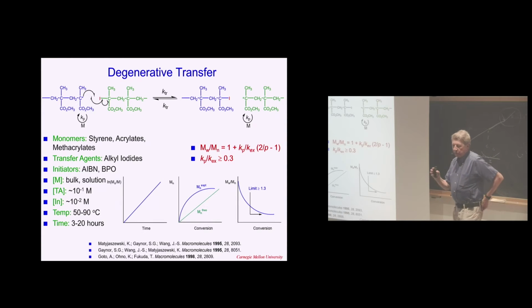So I will give you some examples of these reactions. One of the probably simplest is really with alkyl iodides. It is not a very good system, but it's somehow working. And you could see here what happens. You take alkyl iodide, which resembles propagating chain end. So this is really the structure of a propagating polymethyl methacrylate. And this radical will take this iodine atom, become itself inactive, dormant, and activate this species, which can propagate a couple of times before being exchanged again.